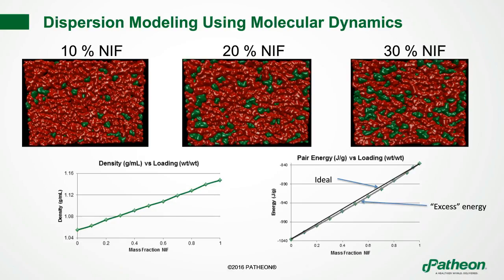What's interesting is that we can extract out what we call the pair energy, and this is the non-bonded energy between all pairs of atoms in the simulation in joules per gram. And this is derived from Lennard-Jones potentials or dispersion forces, as well as Coulombic interactions. So if an atom is charged positively and another one near it is charged negatively, that's a positive interaction from an energy perspective. We can calculate this energy directly from the simulation, and you see that you've got this non-ideal behavior.